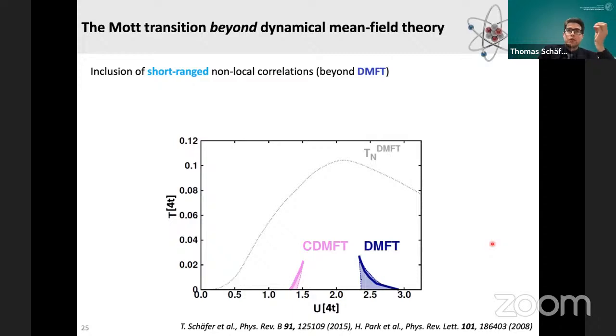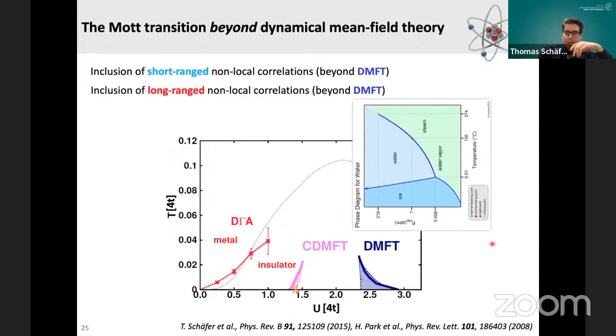What happens now if we include long-range correlations here? And for this, I come back to this phase diagram of water. What we get if we include long-range correlations is that the transition vanishes in favor of a Mott-Hubbard crossover. So a gradual crossover from a metallic to an insulating phase. And please also note that now, regardless of the value of the Coulomb interaction, we always get an insulating state at low enough temperatures. And you can ask the question now, of course, why is this the case?